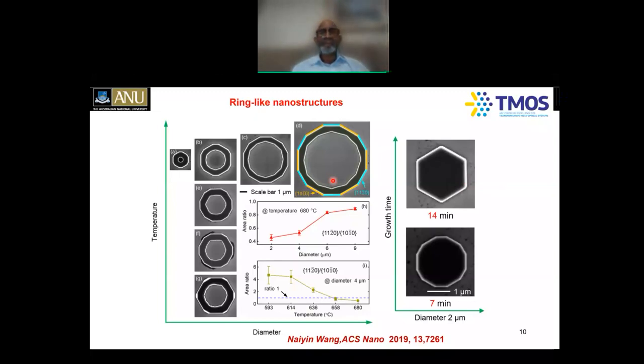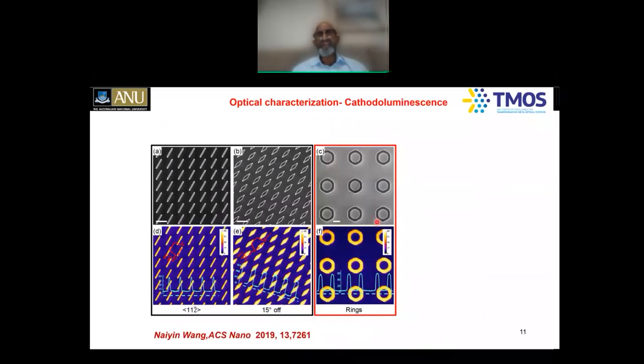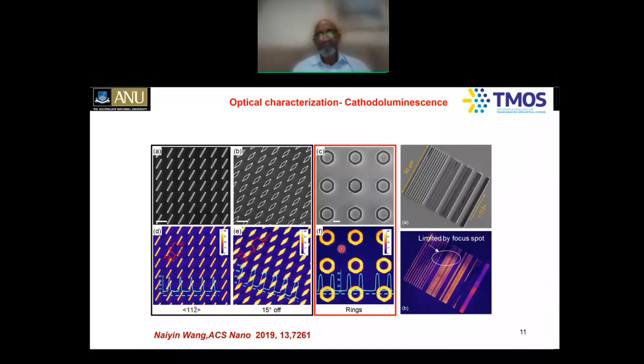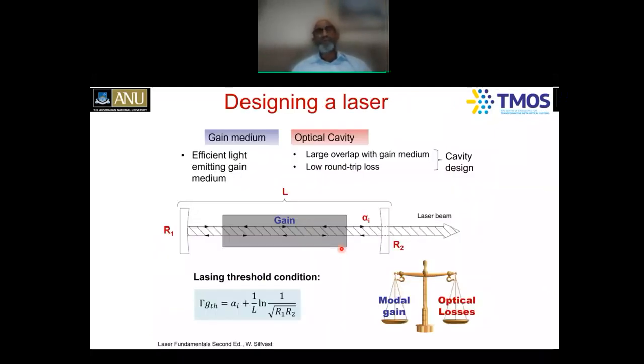So Naiyin Wang has taken these nanostructures and put them into a scanning electron microscope, and excited these nanostructures with an electron beam, and then looked at the light emission, the so-called cathodoluminescence. And you can see that this bottom one is the light emission from all these structures. You can see very uniform light emission, and also very bright light emission, indicating that years of hard work really have paid off in optimizing and growing these defect-free structures. So till now, I've spoken about materials.